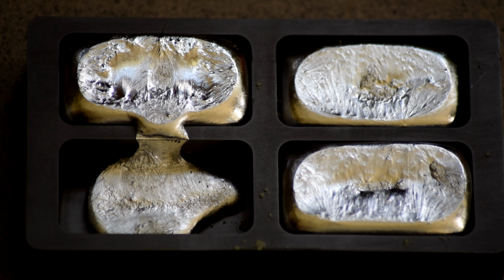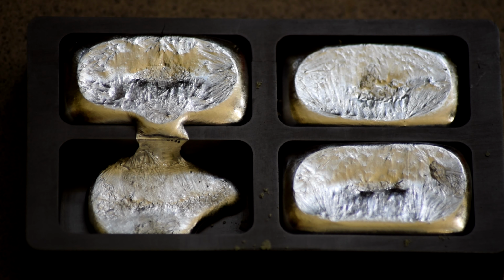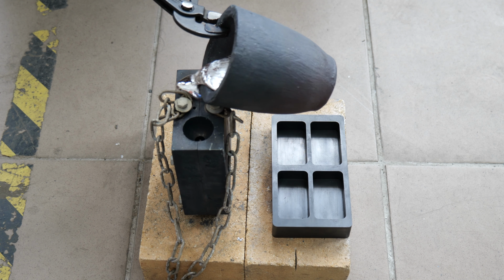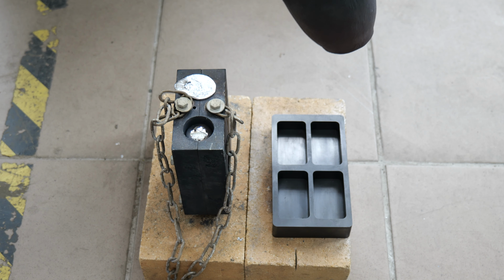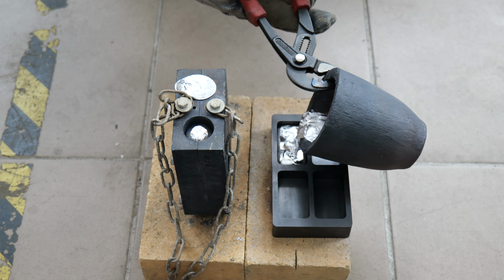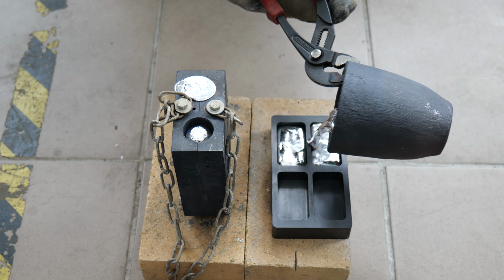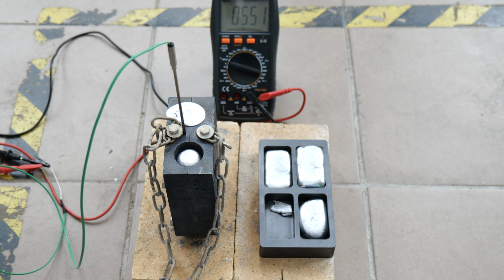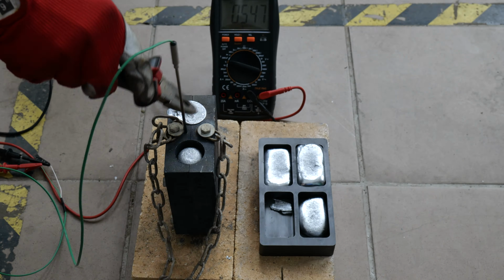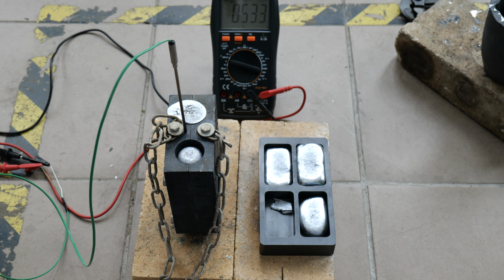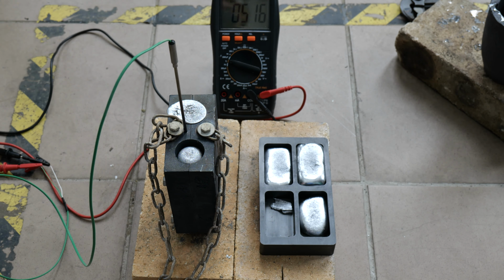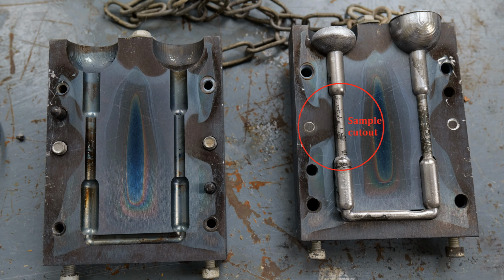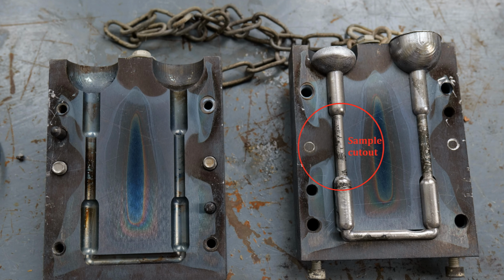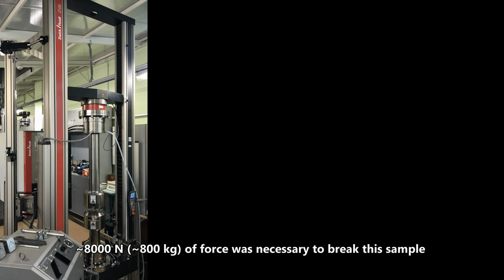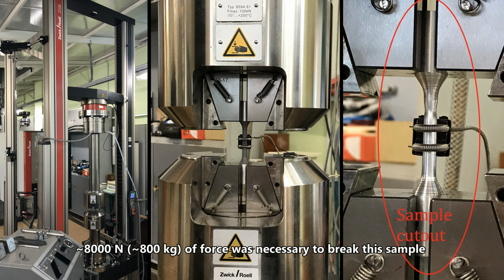The main point of this research is to make stronger alloys. Therefore, one of the main measurements of the sample is its tensile strength. These samples are made in a preheated casting mold, where on one side metal is poured in, which then fills the second column from bottom to top. In that second column, samples of specific size are taken out, then machined, heat treated, and sent to tensile stress testing. Only then do we know whether we have succeeded in making a better alloy.